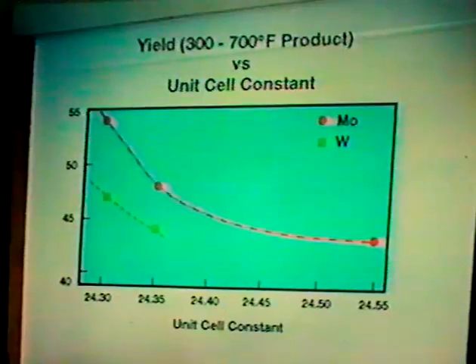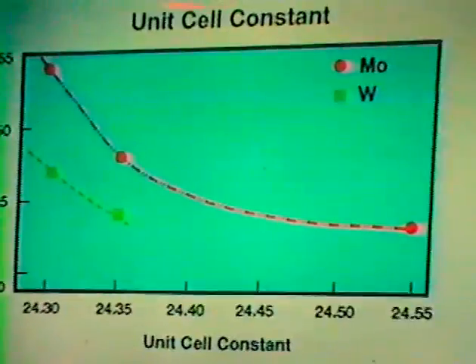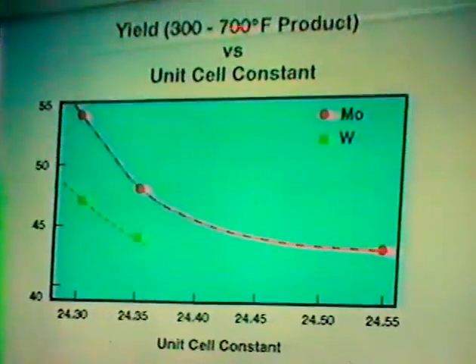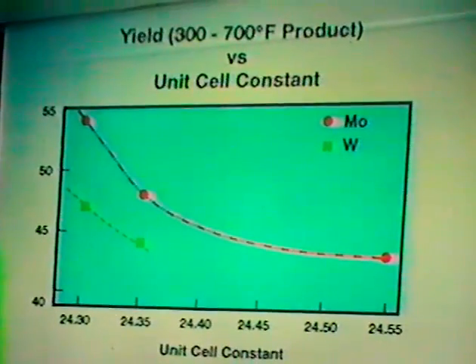These changes also change the product formed, and one can see that going to a smaller unit cell, one increases the volume of the product which boils in the 300 to 700 degree fraction, which is typically the middle distillate diesel and jet fuel range. A decrease in the unit cell increases the amount of this higher boiling product. Also, tungsten gives roughly similar yields, slightly lower.